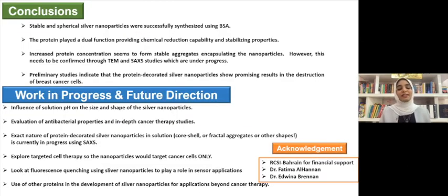So in conclusion, we have successfully formed stable and spherical silver nanoparticles using the protein bovine serum albumin. The protein played 2 parts in this research. It acted as a stabilization agent and a reducing agent to reduce the silver ion into silver nanoparticles. We observed that as we increase the protein concentration, we seem to form a more stable aggregation and encapsulation of these silver nanoparticles, but this does need to be confirmed by using TEM and SAXS studies, which are currently in progress. And our preliminary studies give us really promising results when it comes to our silver nanoparticles and their effect on the breast cancer cells.